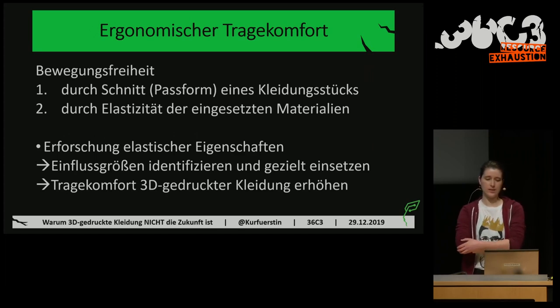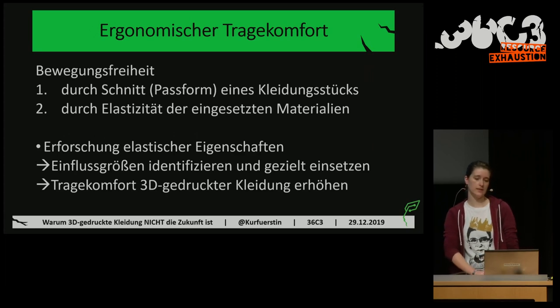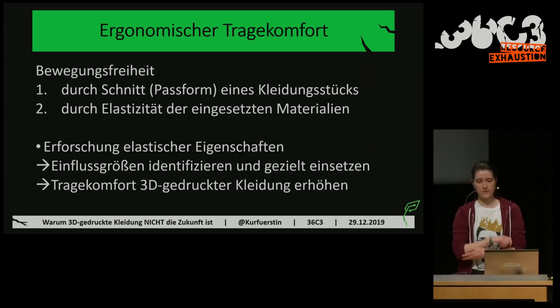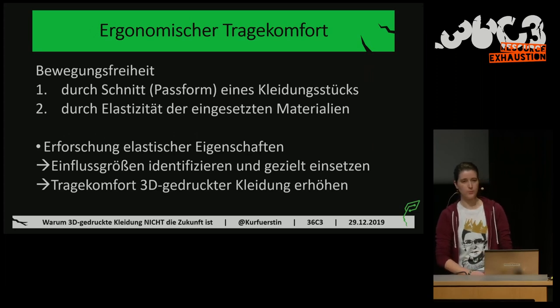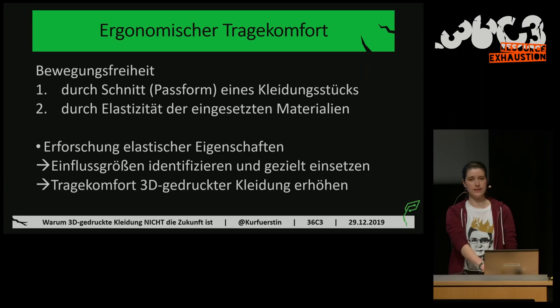If the material used in this place is not elastic, then the surface would either bow out or distort. So if you have a very tight sleeve and the material isn't elastic, and I do this all the time, then it'll take that shape at that point, and it won't look nice. So we need a material that springs back into its original shape once we straighten out our arm. If the surface isn't elastic at all, it isn't that good for clothing uses. But you can compensate for this with cut. If the piece of clothing is wider, the lack of elasticity is not as significant.